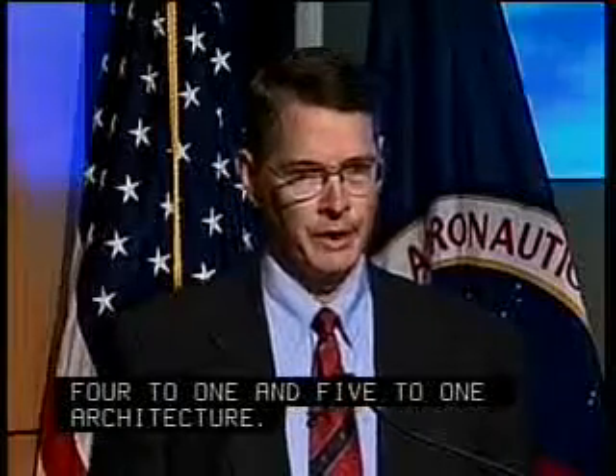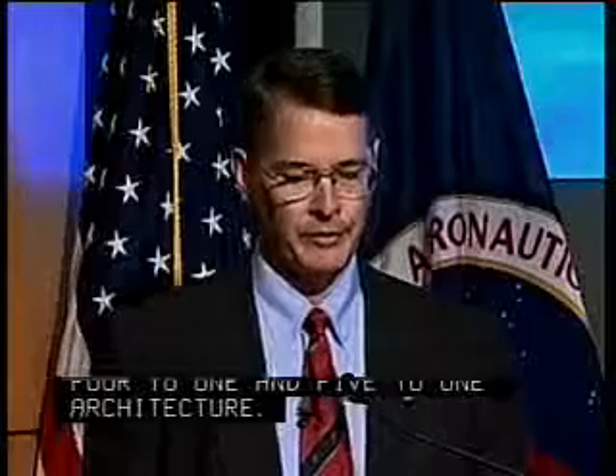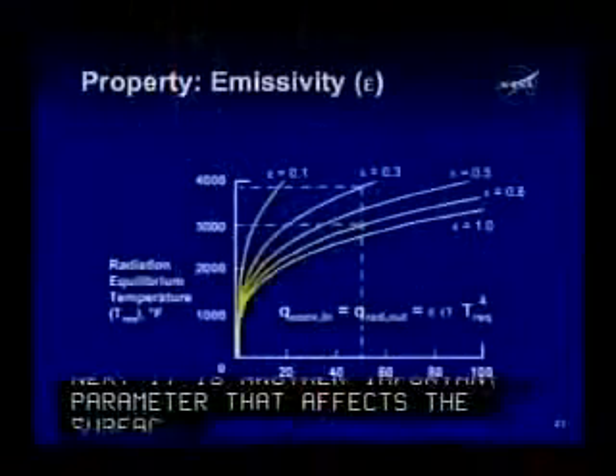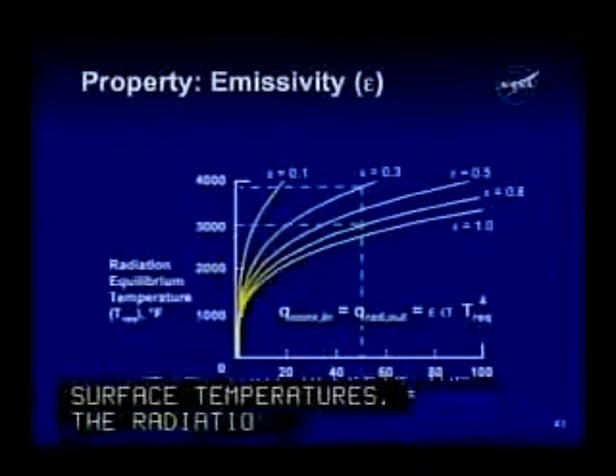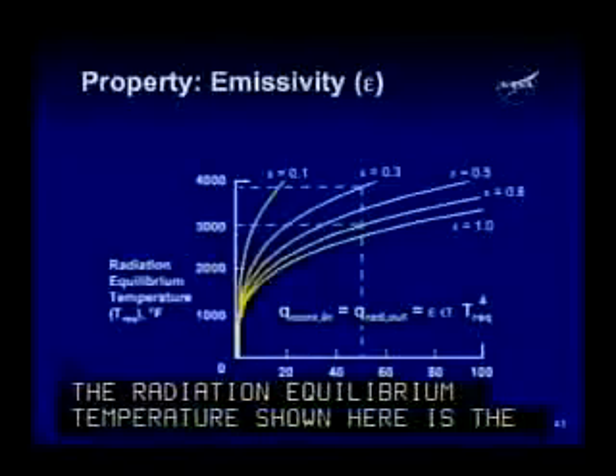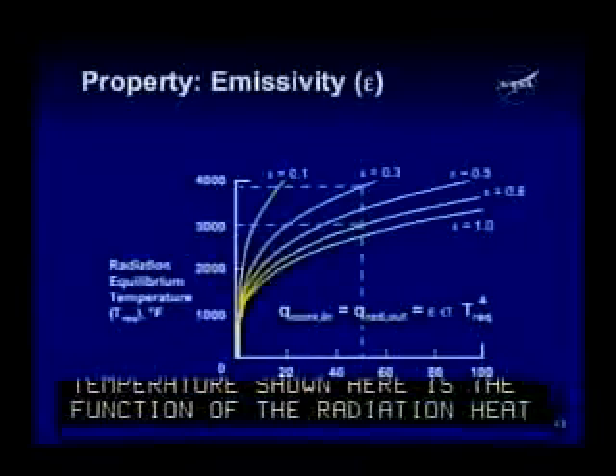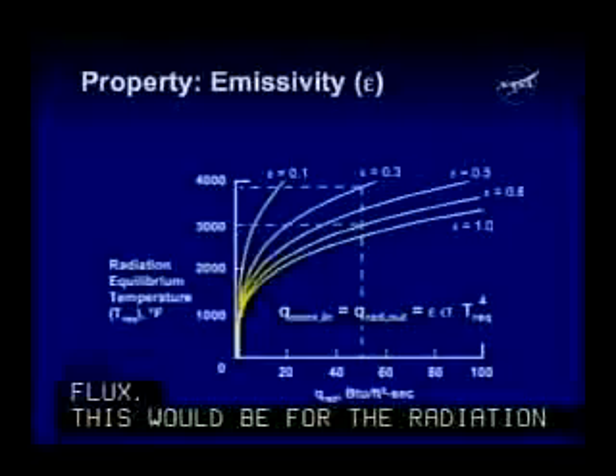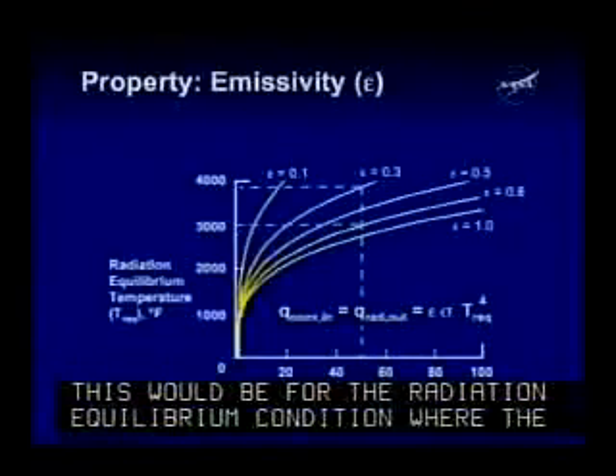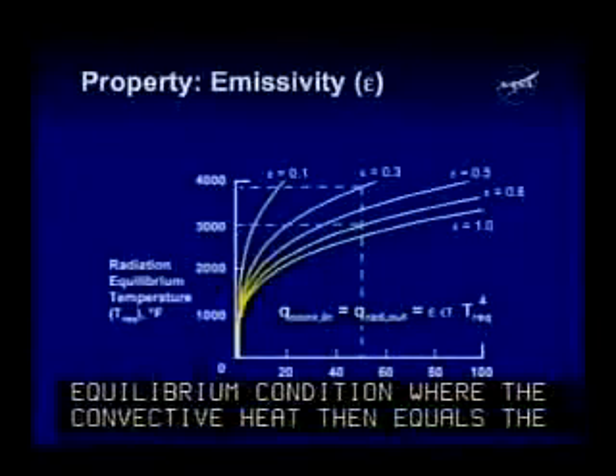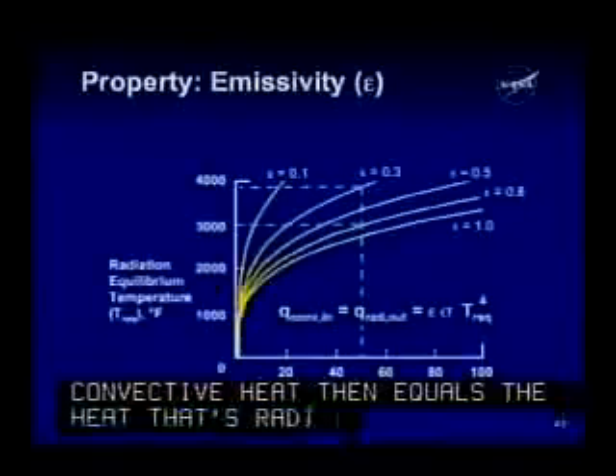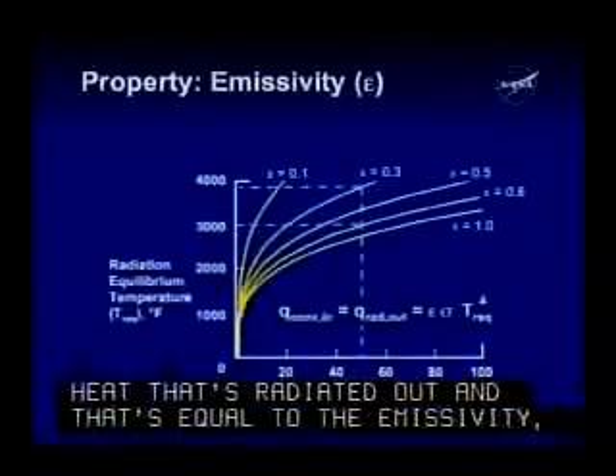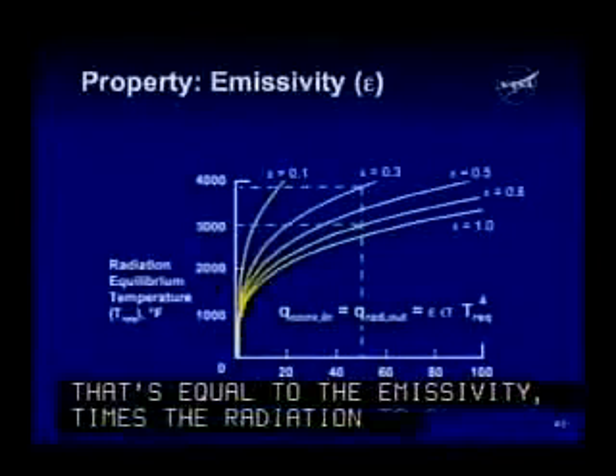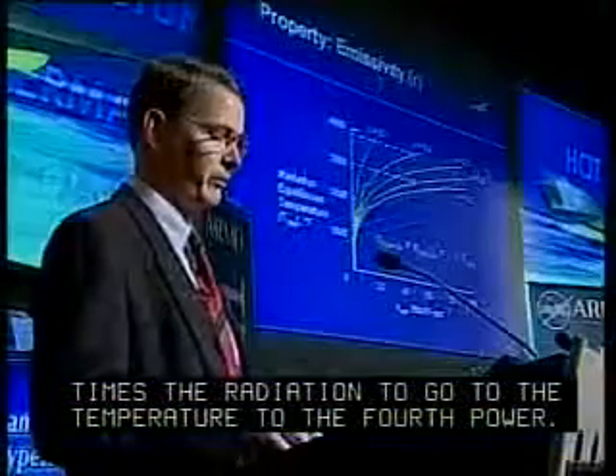Emissivity is another very important parameter that affects the surface temperatures. The radiation equilibrium temperature shown here is a function of the radiation heat flux. This would be for a radiation equilibrium condition where the convective heat in equals the heat that's radiated out, and that's equal to the emissivity, epsilon, times the Stefan-Boltzmann constant, times the radiation equilibrium temperature to the 4th power.